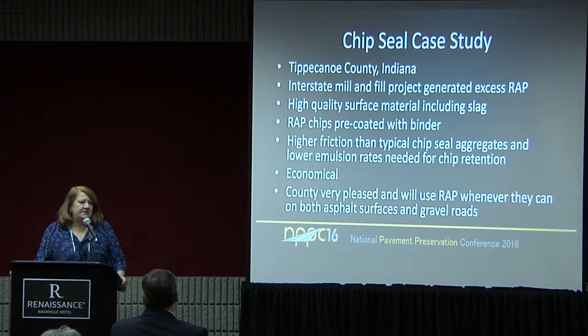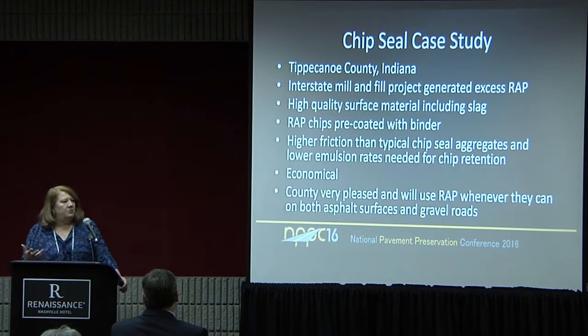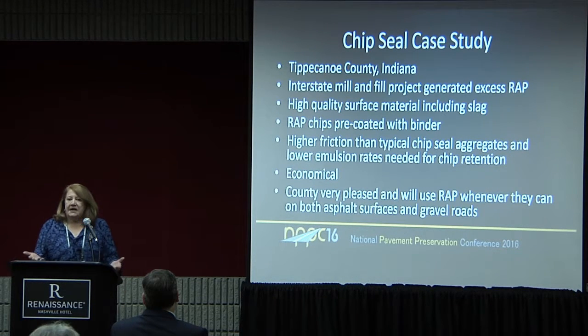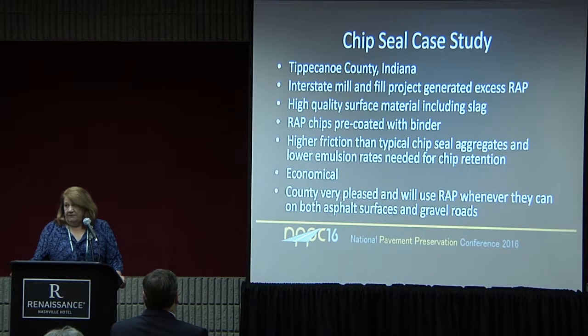They found that, since the RAP chips were pre-coated with binder, they used less emulsion in their chip seal. They got really good friction numbers. It was very economical for them because the contractor needed to get rid of this material. The county was really, really happy with it, and they are going to take advantage of using RAP whenever they can.